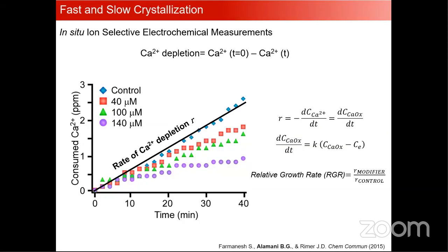All right, next we also tried to look at how fast these crystals are growing. Do they grow really fast, or really slow in the presence of zinc? We used in situ ion selective electrochemical measurements, which detect the presence of free calcium ions in solution. The depletion of those free ions is commensurate with the growth of the crystal. If you introduce more and more inhibitor, in this case zinc, the rate goes down.